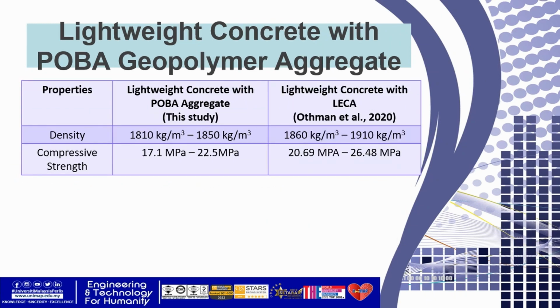And this is a comparison between the lightweight concrete incorporating POBA geopolymer aggregates and the lightweight concrete incorporating LECA, which is the commercial lightweight aggregate. The density results are comparable, in the range of 1,800 to 1,900 kg per meter cube. And for the compressive strength, you can see that it is still comparable to the commercial LECA.